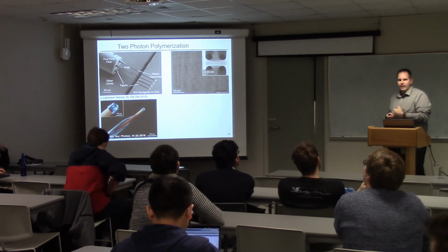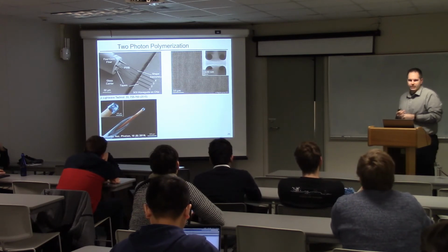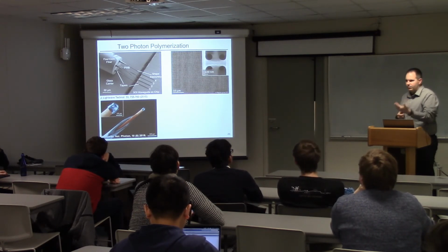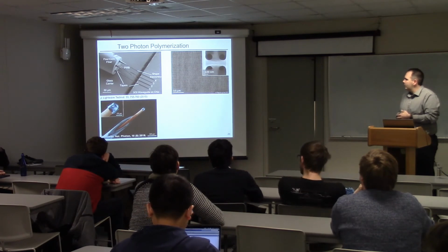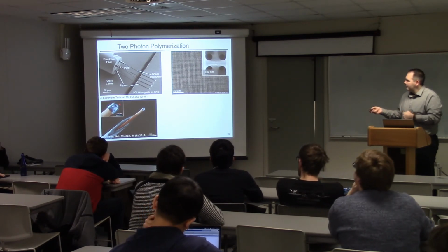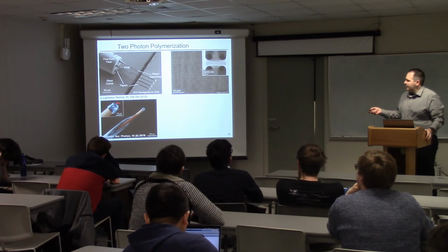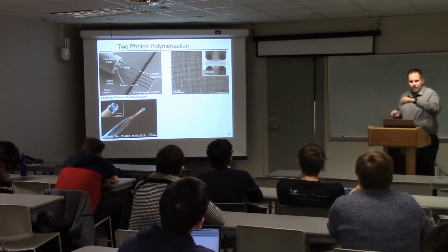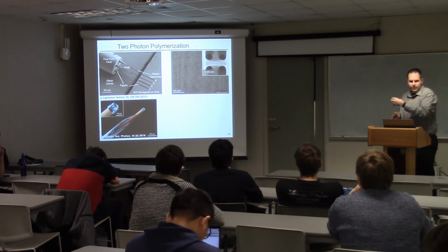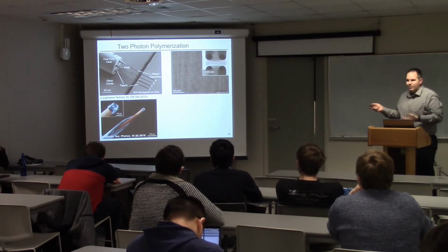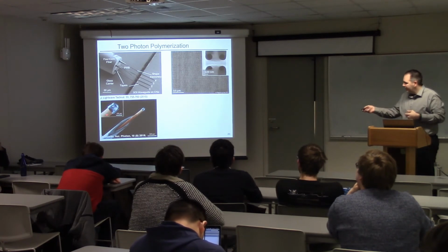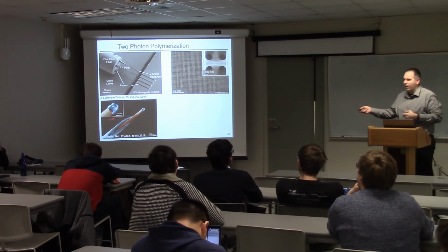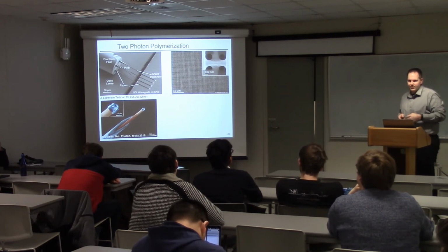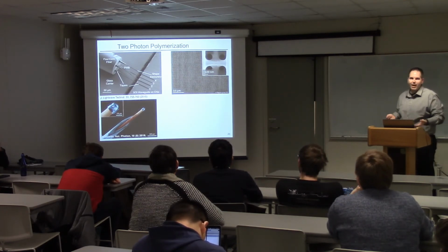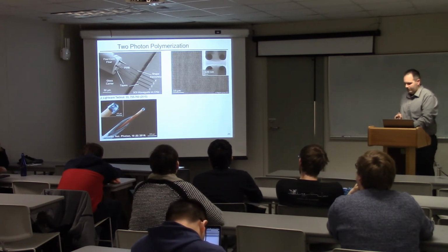And they do that to correct for the higher order aberrations that one encounters when you try and see through different media. And so using this 2-photon absorption mechanism, they were able to put a droplet of polymer and then laser scan and harden this material, develop it, and have this triplet lens design on micro scale. So you can see the 100 micron scale bar here, building micro optical elements this way, and building it on the tip of an optical fiber that will then be inserted inside the human body for imaging.